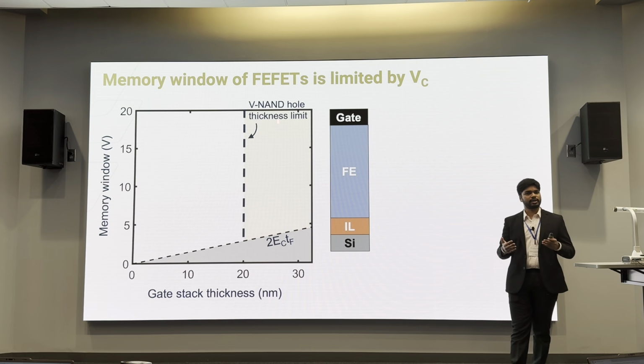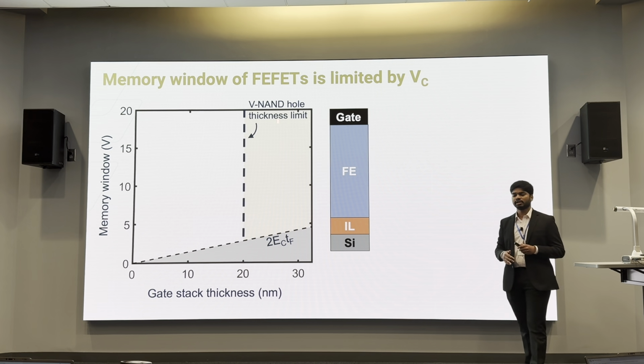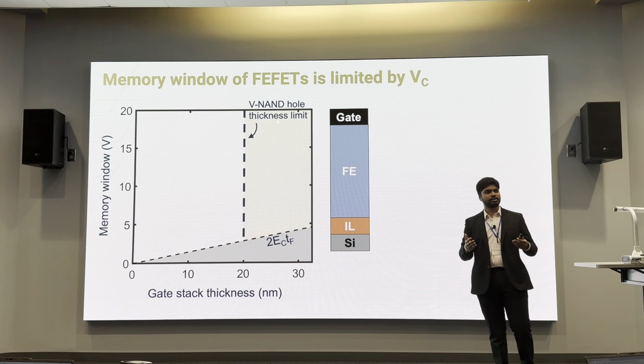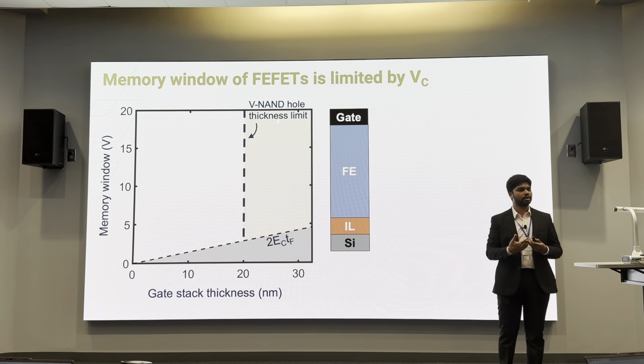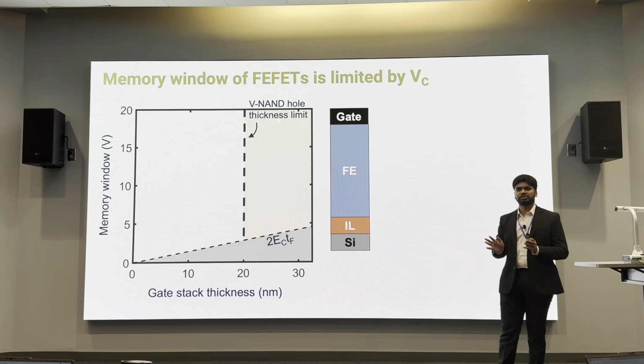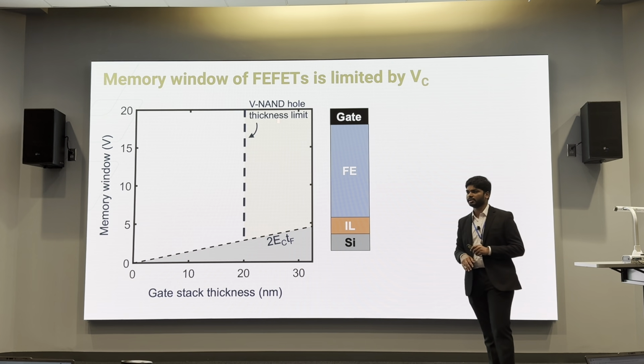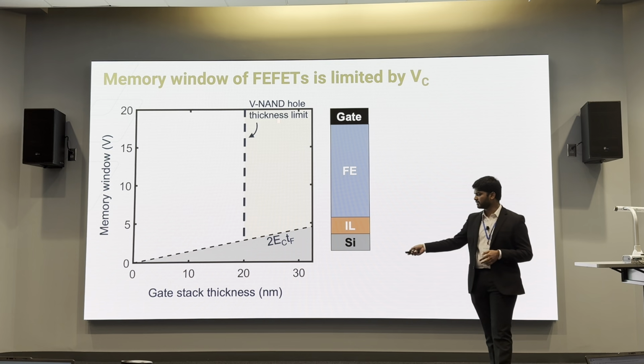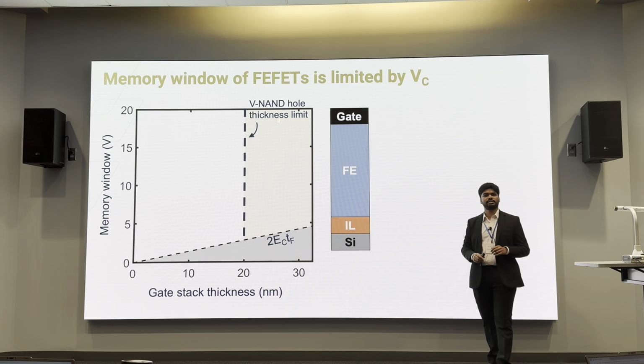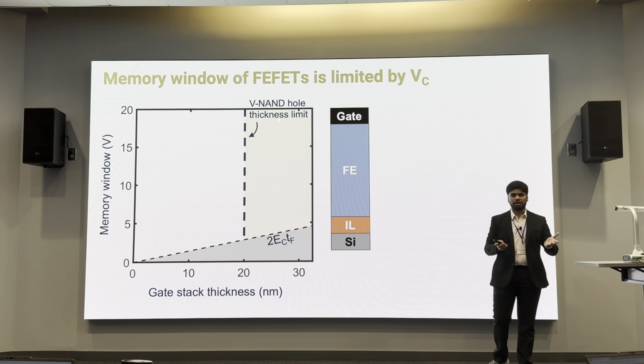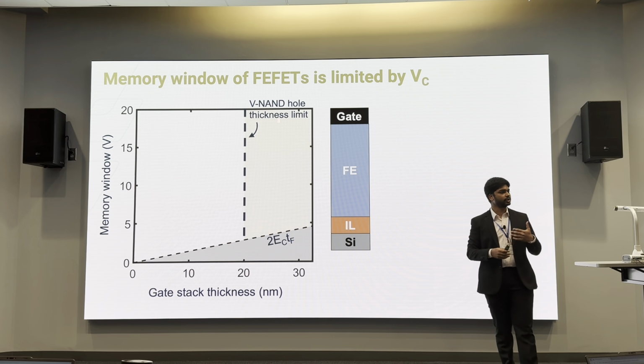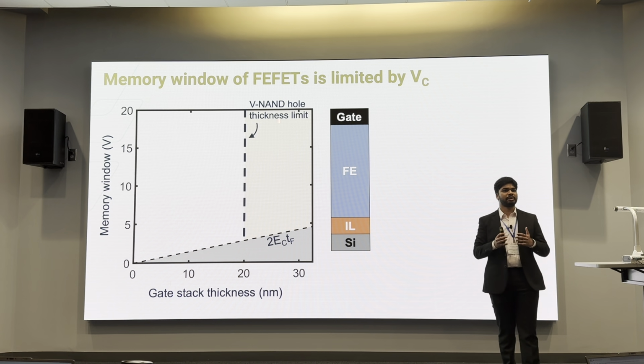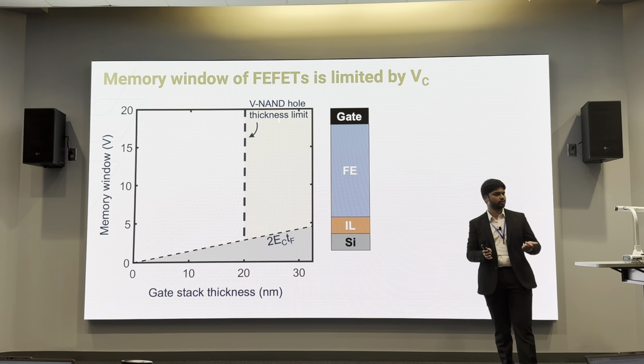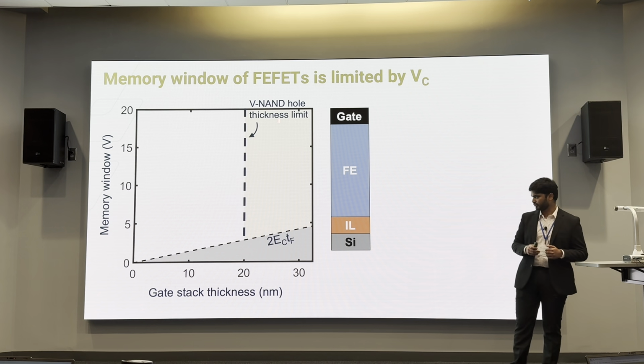Anyone who has worked in ferroelectric field effect transistors will tell you that the memory window of a ferroelectric field effect transistor is limited by the coercive voltage and in turn the coercive field. And hafnium zirconium oxide, which is the stock standard material that we use, has a coercive field of close to 1 to 2 megavolt per centimeter, which at NAND compatible thicknesses of about 20 nanometers limits us to 3 volts in memory window. As I mentioned earlier, today's products are QLC compatible, so we require memory windows upwards of 7.5 volts in order to do multi-level operation.